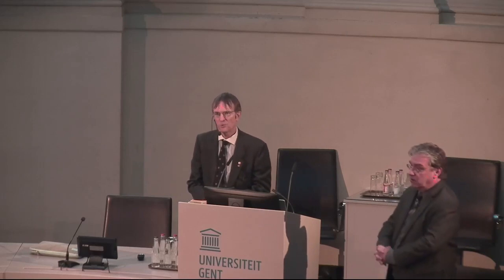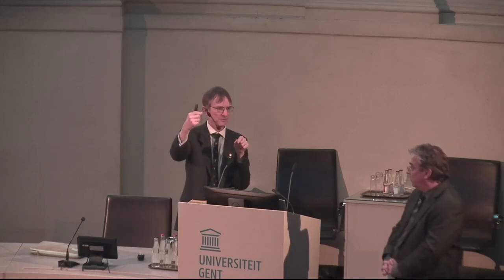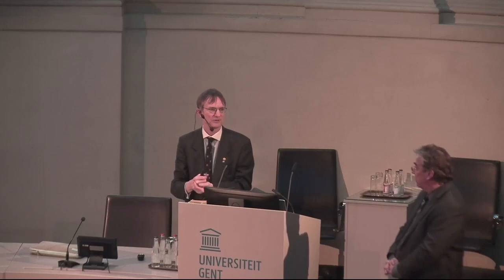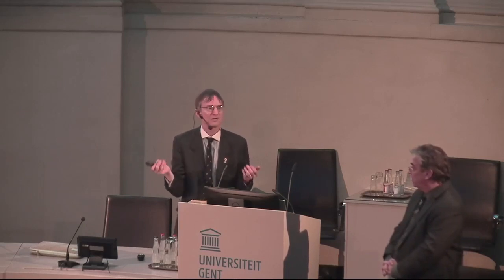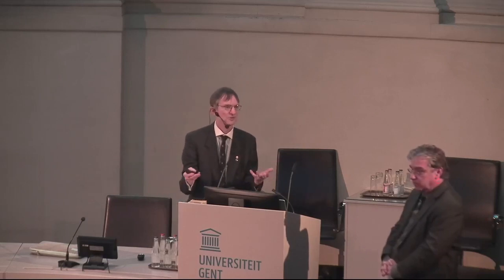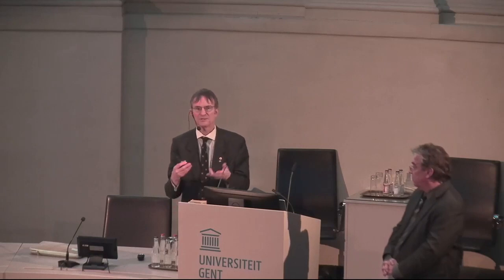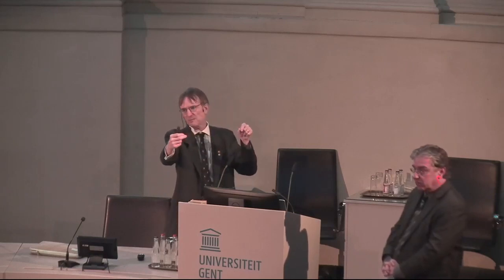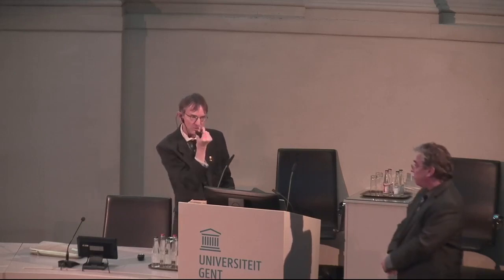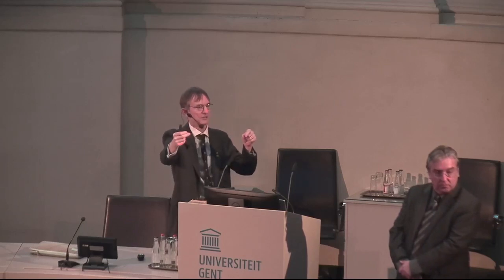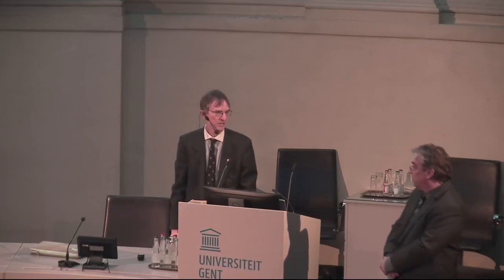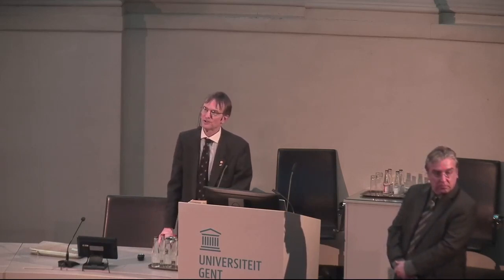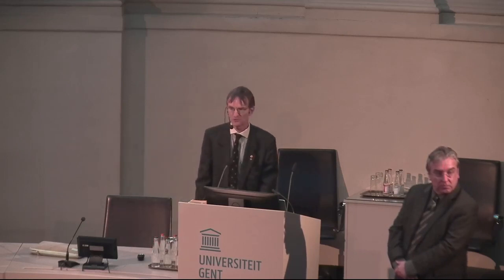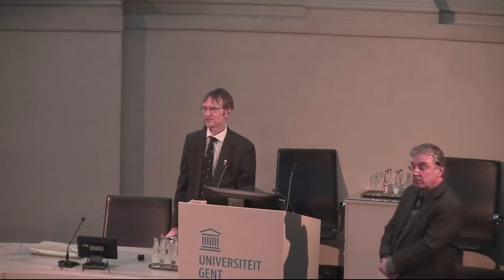And so the quickest answer is to point you to the classical 1941 Rosenthal solution, where you can quite easily derive the length of the melt pool as a function of the power input and the speed and the thermal diffusivity of the material. And what you find is that the thermal diffusivity of almost anything we work with is not that great. I mean, aluminum is about as good as it gets, but most things like titanium alloys and steels and nickel alloys, as soon as you're going at a meter per second, the melt pool can be easily a millimeter long compared to, say, 200 microns wide. They get very stretched out, which also, by the way, for the mechanical engineers, has implications about to what extent you could think about using feedback loops as opposed to having to do things via feed forward. That's a whole other discussion, of course.